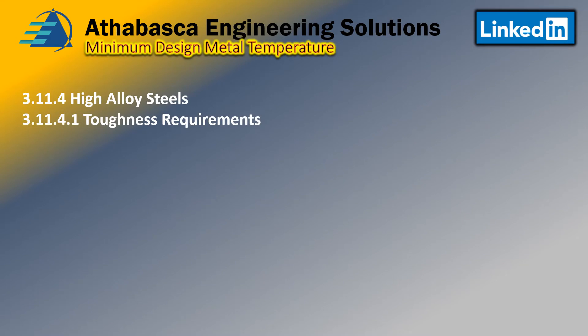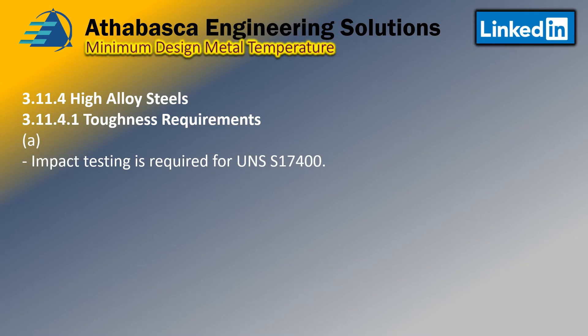There are a few rules regarding toughness requirements, which are of course related to the MDMT. First, impact testing is required blanket for S17400, which is known in the industry as 17-4 PH stainless steel, or martensitic precipitation-hardened steels. This is likely because the microstructure is sensitive to heat since it's precipitation hardened, and they want to preserve its corrosion properties, toughness, and strength through welding.